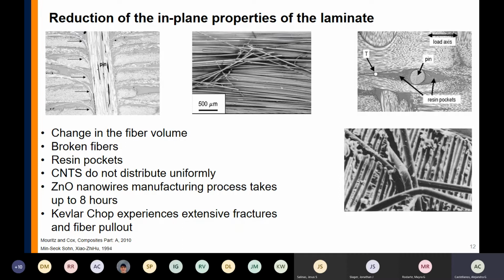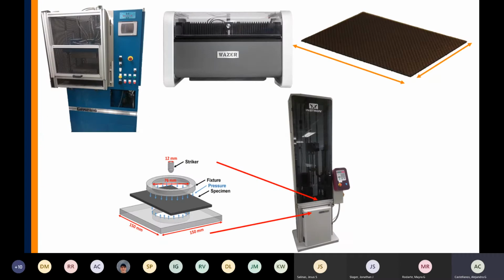And in the case of the zinc oxide nanowires, it takes a long time to process all of them, around 8 hours. And also, the way that we grow the zinc oxide nanowires on the fibers, we use some beakers, and the beaker size is obviously one of the biggest limitations to make this process work on a larger scale. So those are the problems that we have.